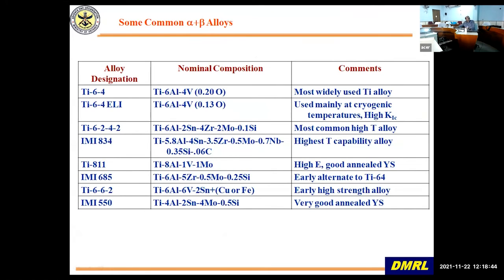These alloys, for example, Ti6Al4V. There are two grades. One is the normal grade, which has a higher amount of oxygen, and then a grade which is called the 6,4 ELI, which has a lower amount of oxygen, 1300 ppm of oxygen. This is for formability and cryogenic applications.